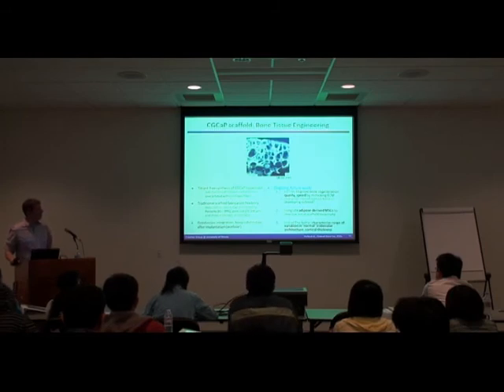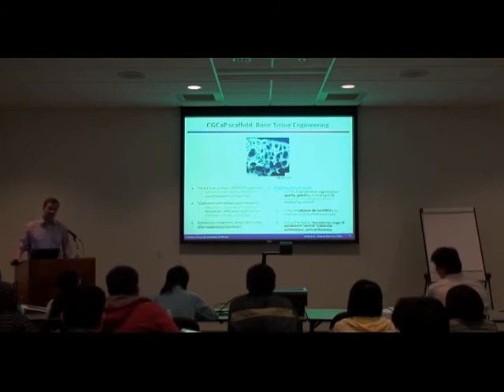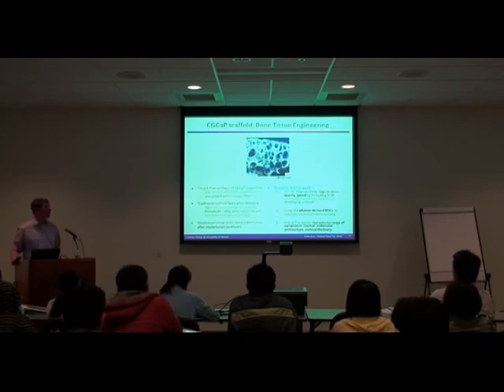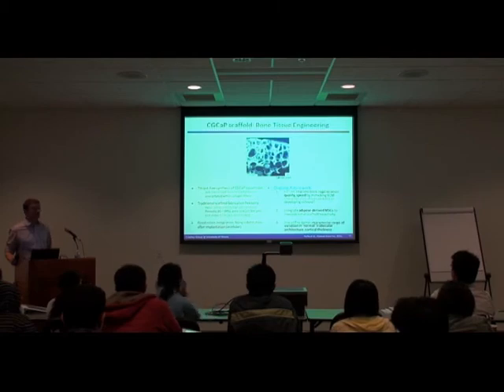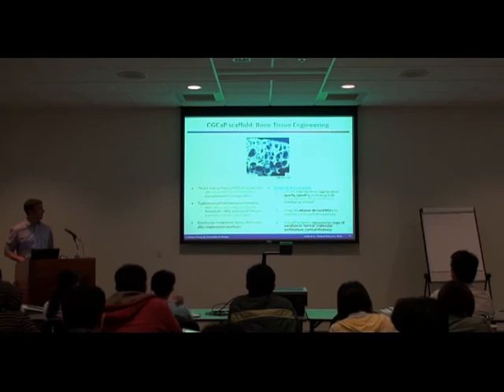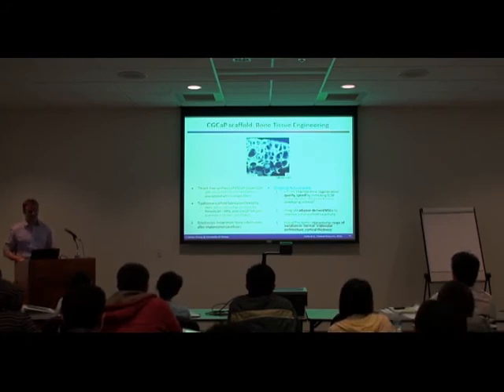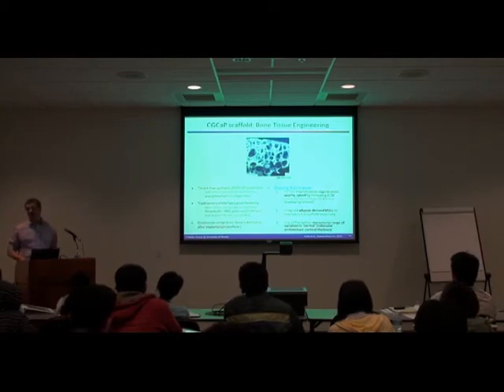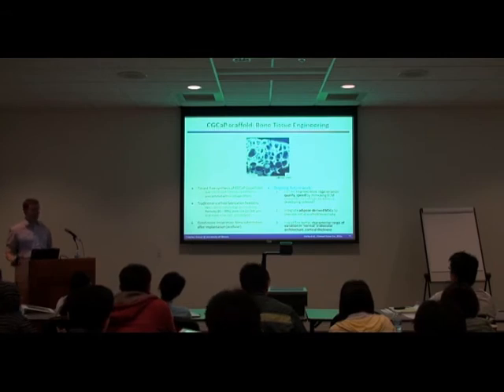So the nice thing about bone is that we think of trabecular bone. It's this nice low-density open cell foam. Granted, it's a mineralized low-density open cell foam, but we've worked a great deal in developing fabrication processes to produce collagen-based scaffolds that have a collagen backbone with an integrated nanocrystalline calcium phosphate to mimic the local structure you see of bone itself. And it's done with this triple-phase co-synthesis process where we take our collagen and our glycosaminoglycan and calcium salts and a phosphoric acid, and by titrating the amounts correctly, you can actually precipitate out nanocrystalline calcium phosphate along with the collagen that you're precipitating out of solution during the fabrication.